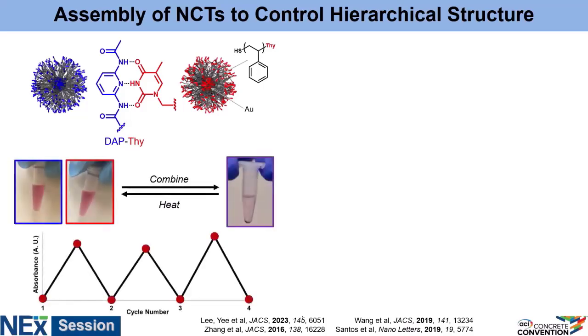If I synthesize these particles and put them into organic solvent like toluene, they will remain more or less indefinitely soluble, just suspended in that toluene solvent. But as soon as I combine these complementary particles, they will immediately aggregate and precipitate out of solution because the hydrogen bonds are now linking them together. Hydrogen bonds are very weak though, so we can easily disrupt them by simply heating them up — the temperature depends on the actual design of the particles, but we're talking 40 or 50 degrees Celsius. If we heat them up, they dissociate and go back to being free in solution; if we cool them down, they reassemble, and we can cycle through this without actually changing anything about the properties of the material.